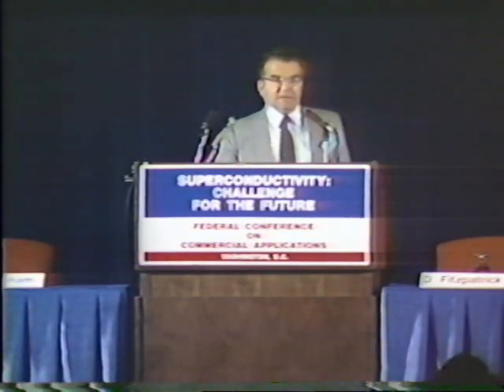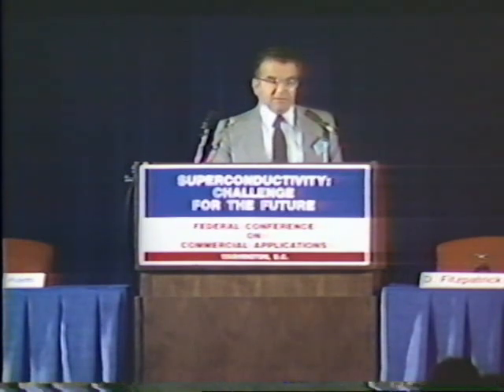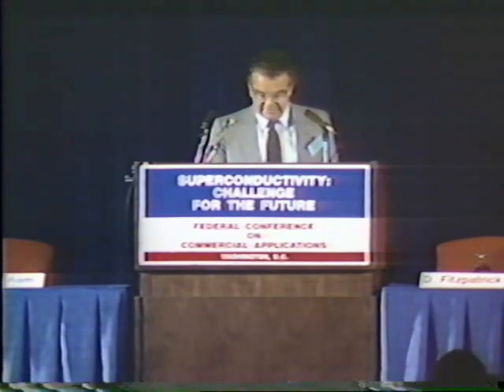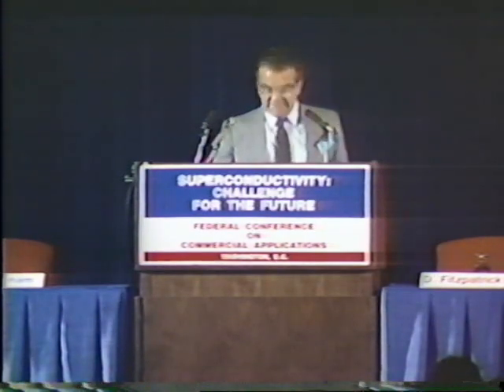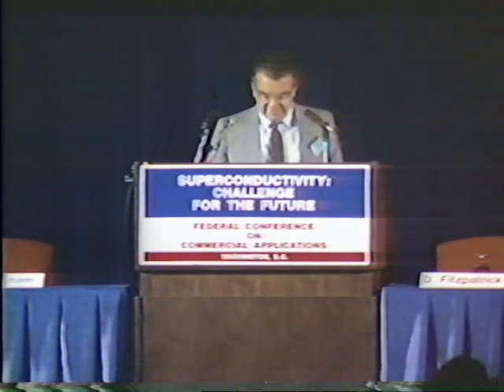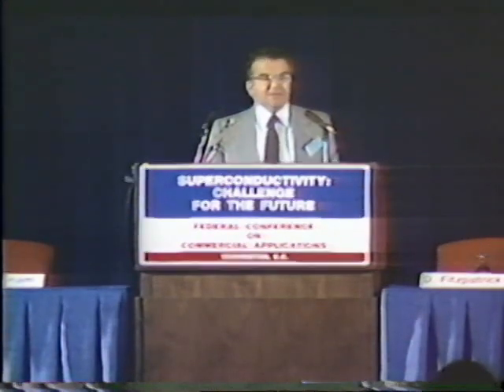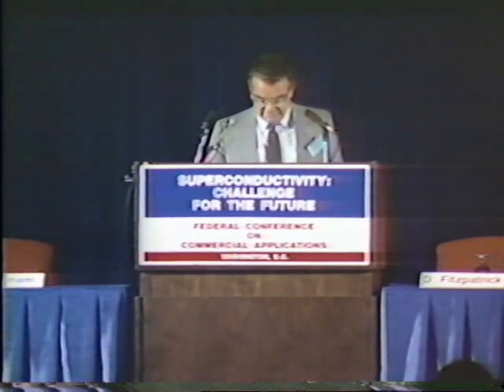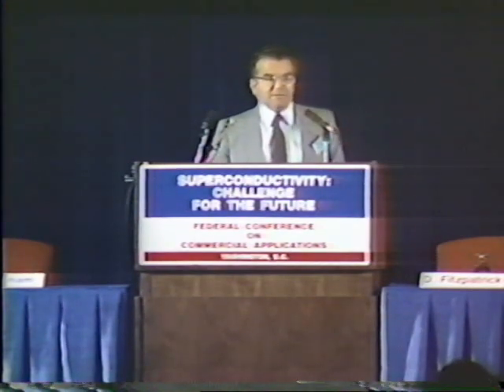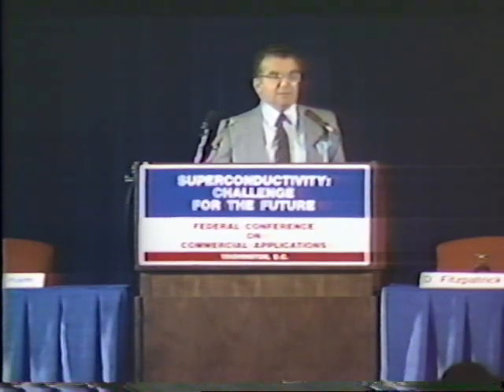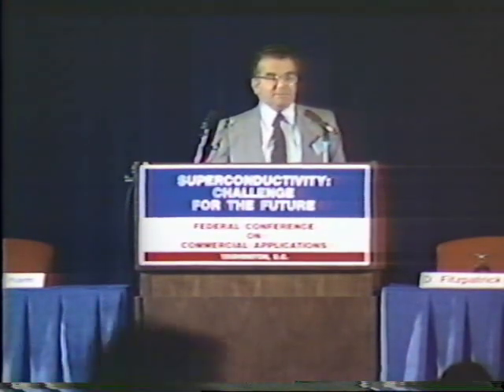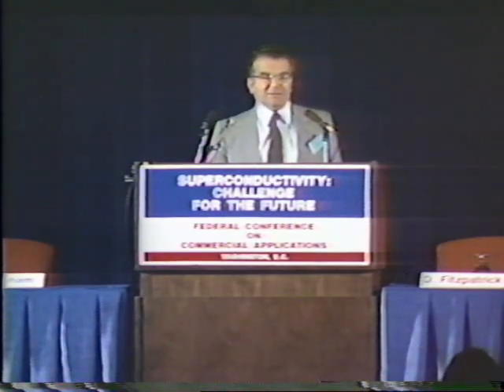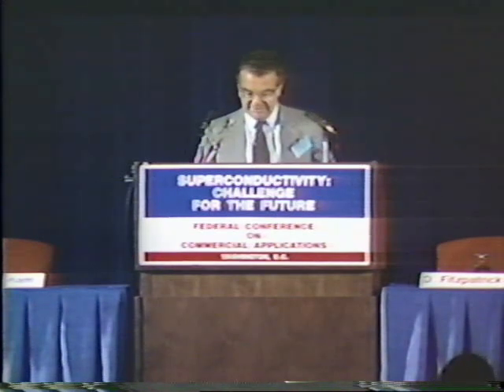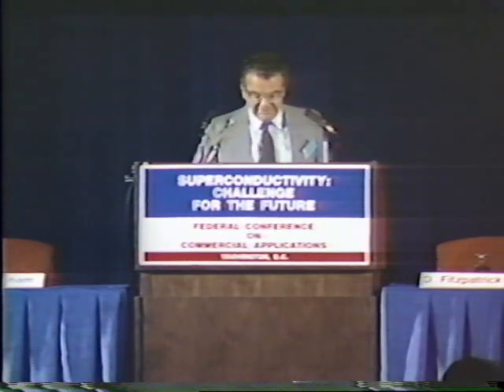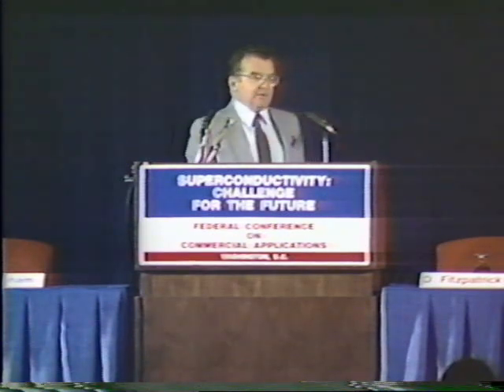So any heating in vacuum of a film of this material is not only going to destroy the superconductivity, it's going to destroy the conductivity. Now, this is a challenge for processing. It is also, I believe, an opportunity for use. In fact, if you sit there, you can actually think of devices, crude devices, that rely on this oxygen sensitivity of the transition temperature. Now, we heard a lot about hybrid technologies, semiconductors plus superconductor. This material is a hybrid material. Depending on its oxygen content, it is either a semiconductor or a superconductor, or maybe both if you don't process it very well. Now, you can restore superconductivity on the next slide.